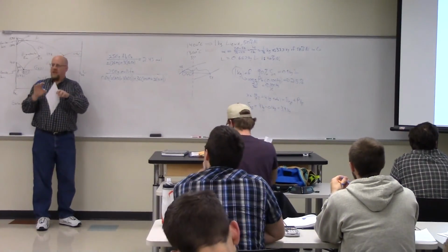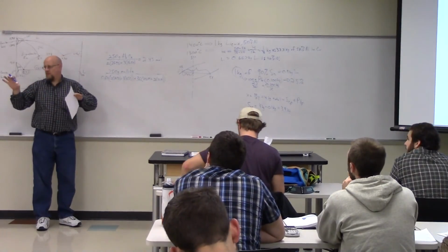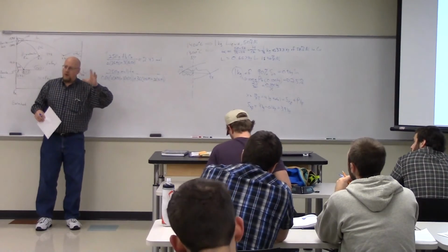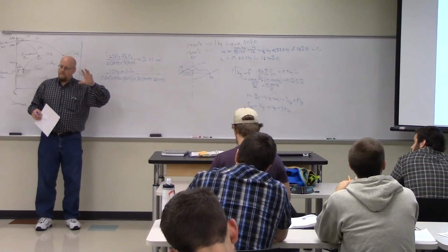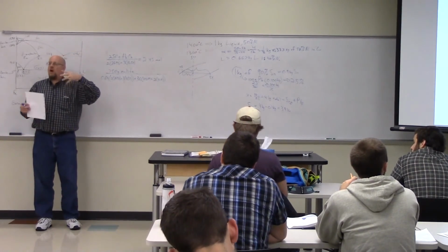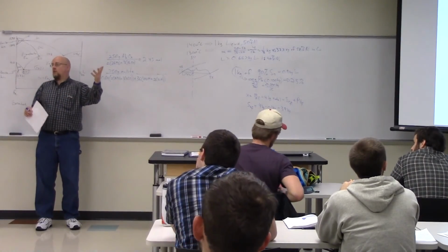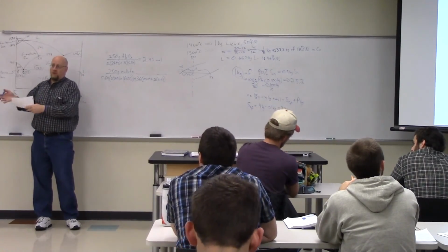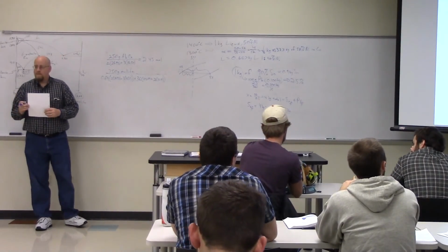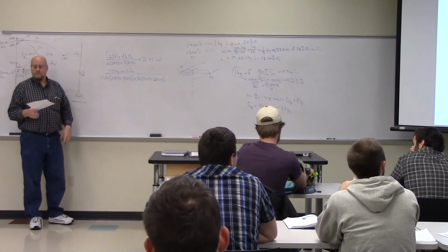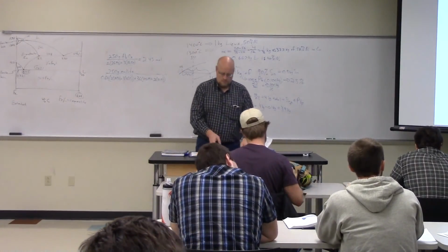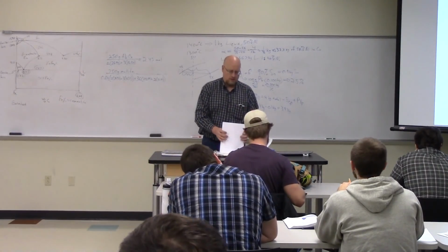Because what happens is the Al2O3 separates: some of it stays as Al2O3 by itself, and some of it mixes with the SiO2 to form mullite. But not all of it can form mullite. You only have enough SiO2 to form a certain amount of mullite. All that's left over forms alumina as a separate phase. So there's actually two different materials there. Mullite has different properties than alumina does, yes.